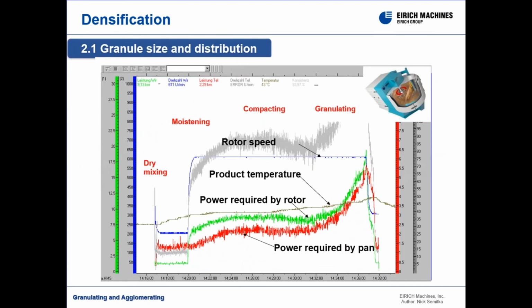This graph shows that sometimes it takes time and energy densifying powders before the granulation process starts. Here we ran the mixer at a slow speed for 12 minutes. At that point, the granulation process begins. Moisture gets trapped in the hollow pores between the small granules, and by introducing energy, densifies the material, filling the hollow pores between the granules and driving the moisture to the surface. And that's when the granulation process starts.